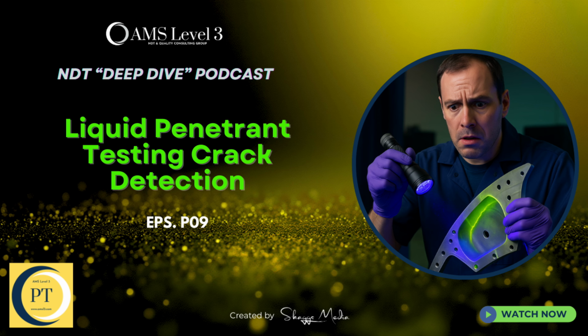Does the shape give clues? Absolutely. The morphology, the shape, and appearance of the indication is key. For instance, cracks almost always appear as thin, linear lines. Makes sense. And you can sometimes get a hint about the depth, too. A deeper crack holds more penetrant, so the bleed out might be a bit wider or maybe brighter and more